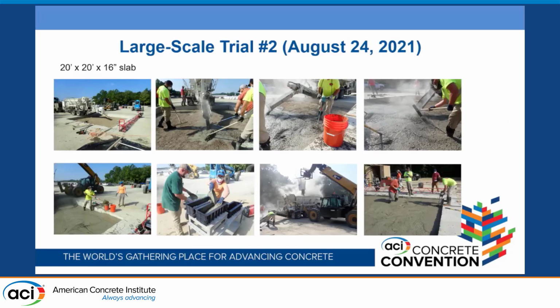So these are a lot of pictures, but we did a 20 by 20 by 16-inch slab. It was a hot day, I remember that. So there's our slab, there's our mixer. There we are getting started pouring. There we are, I brought out handheld mixers to help with any potential layering. But as rapid set's going down, just more raking. I'm collecting the QC sample. There they are making flex beams and cylinders. That's just the SVM, simplified volumetric mixer, being reloaded. And then there we are getting pretty close to the top. Just some more handheld mixing, to make sure that we don't have any unintentional cold joints in the slab.